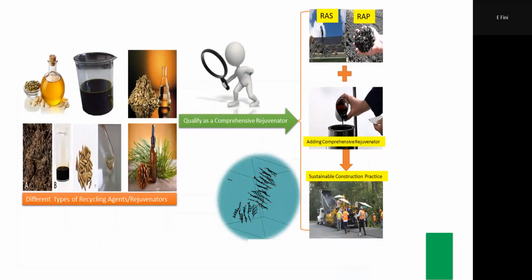Here you can see RAP, which stands for Reclaimed Asphalt Pavement, and RAS, which stands for Recycled Asphalt Shingles. These are aged bitumen. Much like the picture I showed you with all the cracks and wrinkles on top, these are 20, 30, sometimes 50 years aged asphalt, been on the road for many years. These are aged, highly oxidized. Now we want to reuse them, which is a great practice, but you have to make sure their properties are good enough not to compromise your new pavement. So rejuvenators become more and more common and acceptable because we want to improve the properties of the new pavement and still use a large portion of recycled material. It's a win-win. You are recycling more material, and you're still getting superior performance. That's awesome. So when you add the rejuvenator to your recycled material,